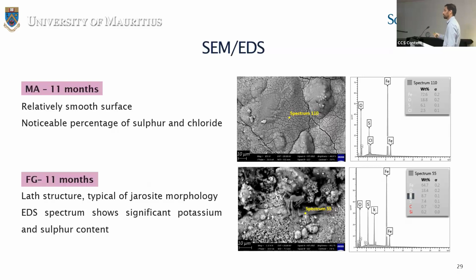Although there is no obstruction for sea aerosol entrainment, there is shielding from the effect of rain at this site. This does not contribute to washing off of pollutants from the surface. That's why you could observe sulfur and chloride on the surfaces, which don't penetrate the rust layer because of lack of precipitation and sorption at this site. At FG, the lath structure was examined and potassium and sulfur were observed, which confirms that this is a jarosite morphology.